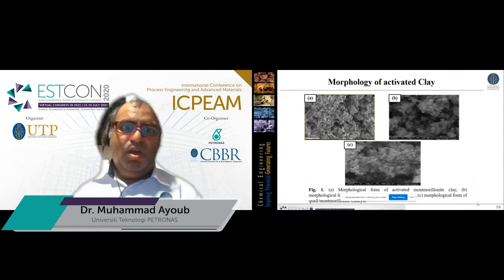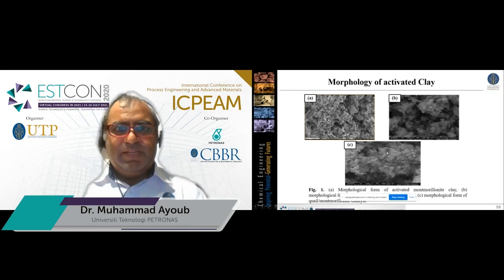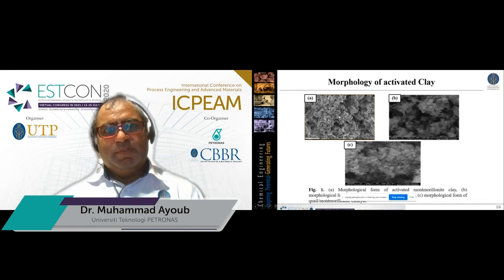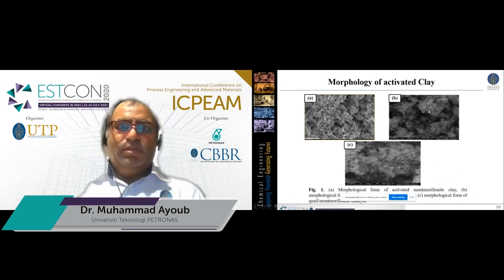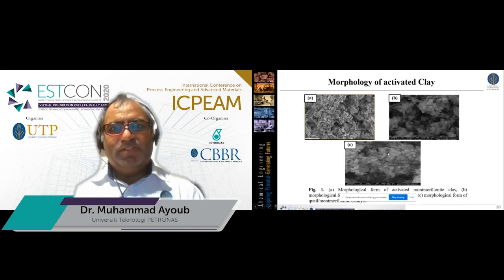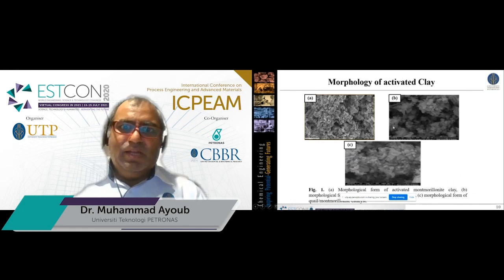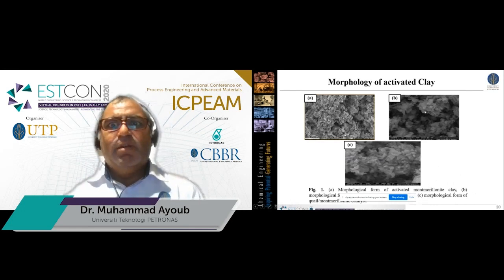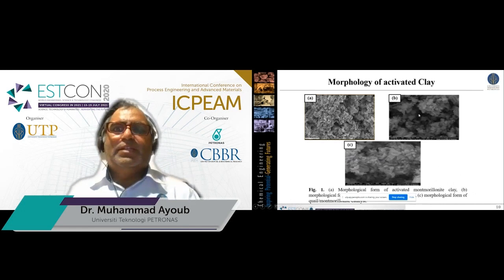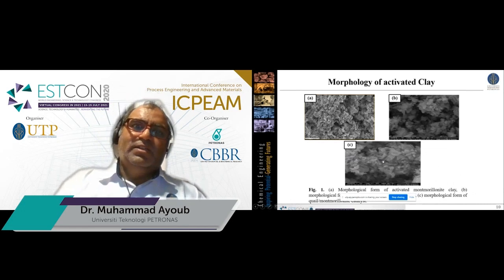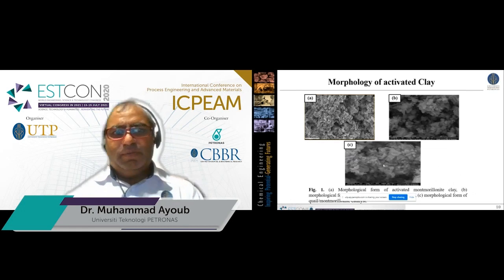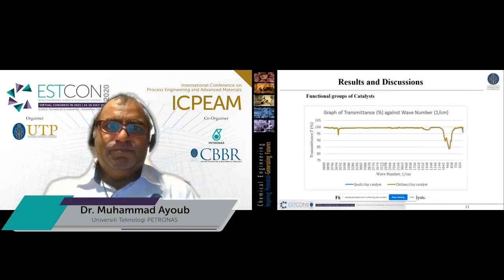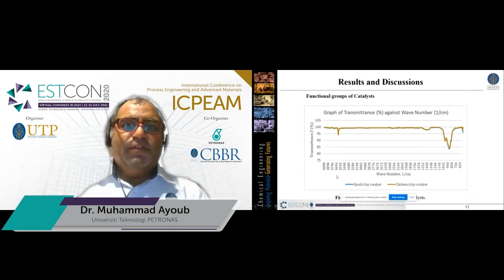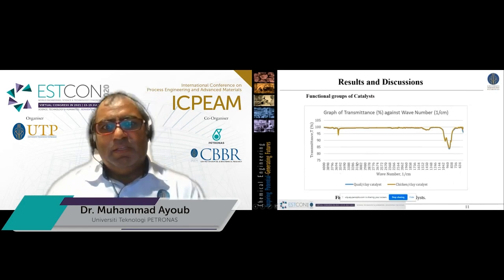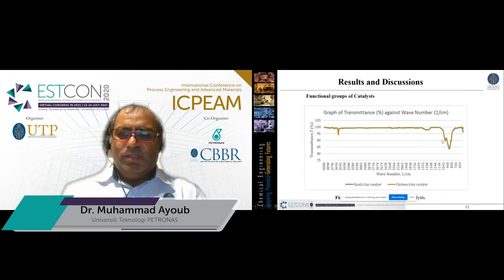In the morphology, we can see the same image of the produced morphology from activated montmorillonite clay. In the first image, A, you can see some spaces, but when we add our chicken eggshell and quail eggshell, you can see the spaces are filled, and some other gaps are available there. It means in our process you can see slightly dark and white areas. So after adding the eggshell, we can say the mixing is there, and the effect of calcium is available there from the same image. Similarly, in the FTIR, we can easily see that the FTIR after adding the eggshell with clay is clearly the same. There is no effect, which means they are compatible with each other.